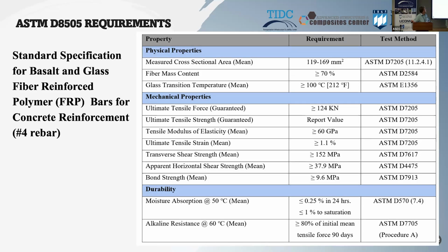That standard, D8505, it's important to recognize that applies to both glass reinforced and basalt reinforced rebar. So it's fairly broad in terms of the type of fibers that can be used for reinforcement. When I go through the slides, I will talk about the requirements, and I will use my 2 sample commercial bars to see how these requirements are met. And I will discuss briefly the test method, the rationale. What are we trying to measure? Why the ASTM standard such and such has been chosen to measure that property.